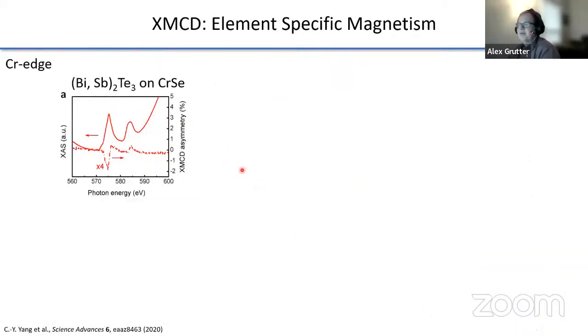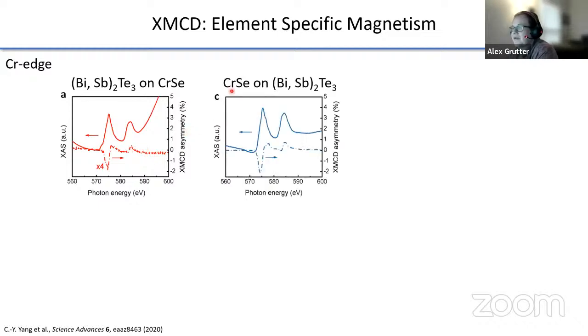And so the final piece of the puzzle then comes when we do X-ray magnetic circular dichroism measurements to get element-specific magnetic information. If we grow bismuth antimony telluride on top, we do see a very, very small chromium magnetization. I would say trace. But then if we grow chromium selenide on top, it's significantly larger. So the growth order again seems to matter here, and you get more of a magnetic signal in the chromium if you grow chromium selenide on top.